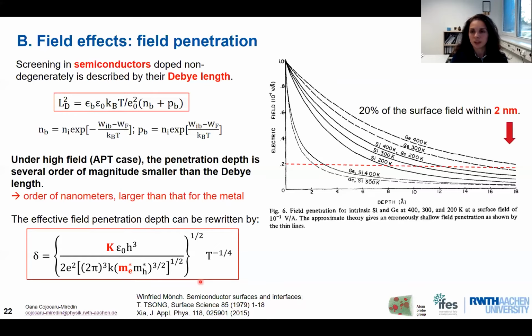And there was a very nice work which has shown a dependence between the effective mass of the electrons and the band gap, and they seem to be directly proportional. So if we have a very small band gap, we have a very small effective mass of the electrons. And with a small effective mass of the electrons, we have a very high penetration depth.